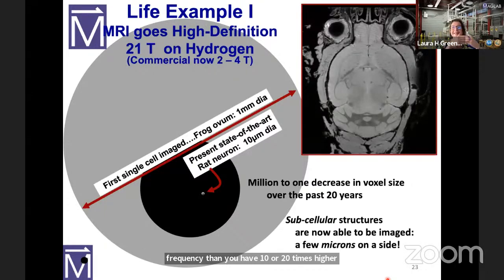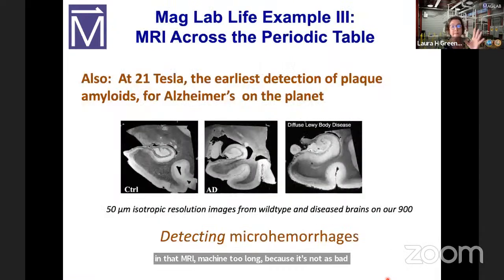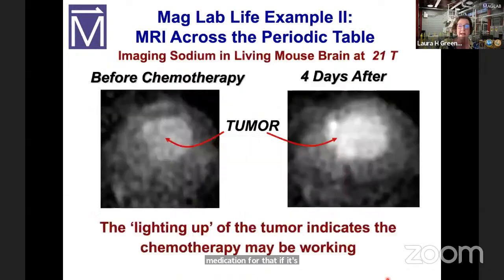But you don't want someone to be in that MRI machine too long, because it's not as bad as a microwave oven, but you just don't want to stay there a really long time. But one example where it's worth the risk is that at 21 Tesla, that's the earliest possible detection of plaque amyloids, which is agreed upon to be a problem for Alzheimer's, a reason why Alzheimer's forms. And the reason why this is useful is because the plaque amyloids that form in the brain actually cause microhemorrhages. So if you have that higher resolution, you can pick up, in this case with 50 micron resolution, early microhemorrhages. So this will be applied later on in the health industry, because if you start getting Parkinson's or Alzheimer's symptoms, it would be worth going in and seeing if you should be taking medication for that if it's an early phase. So this is the earliest detection of plaque amyloids on the planet.